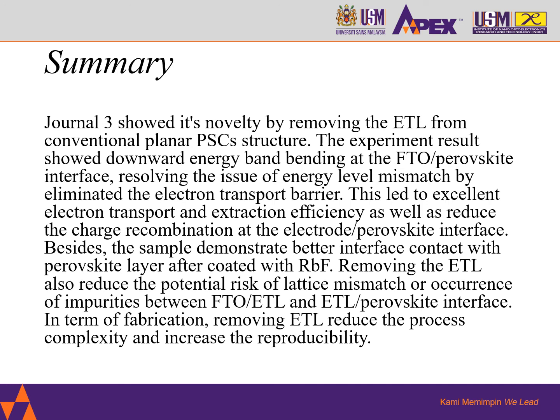Removing the ETL is very beneficial in reducing the potential risk of lattice mismatch between the FTO and ETL, and the ETL and perovskite interface. Also, they are able to reduce the potential occurrence of impurities between all these interfaces. So in terms of fabrication, removing one ETL from the structure definitely reduces the process complexity and also increases reproducibility.